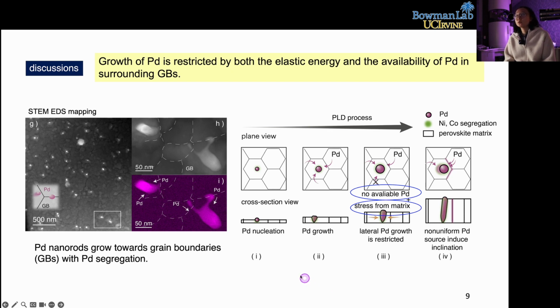Besides, we also do a survey on the plan view of this palladium nanorod sample. So you can see this is the plan view TEM sample. The white dots in the HAADF image represent the palladium nanorod tips. The white contrast parts in the HAADF image do correspond to the palladium. Besides, we find the palladium is diffusing from the grain boundary part to the palladium nanorod part.